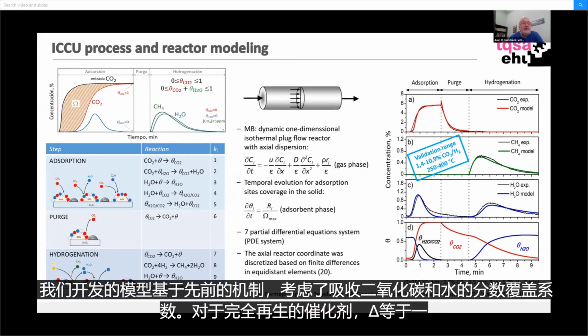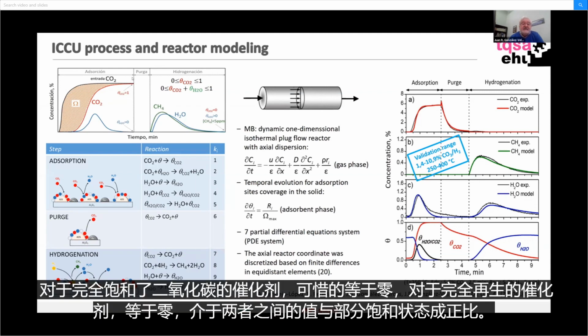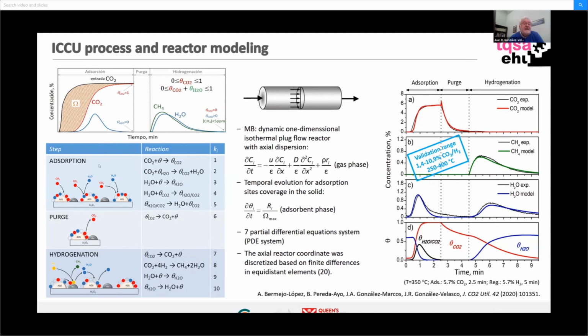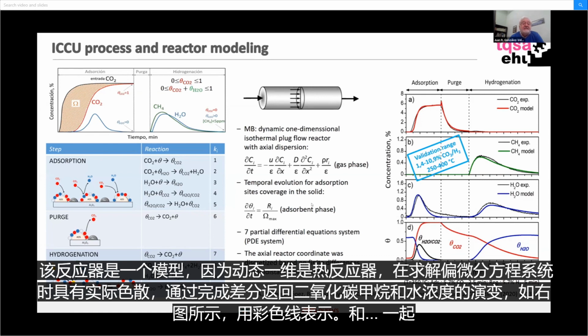The model we developed is based on the previous mechanisms and considers fractional coverage factors for absorption of CO2 and water. Theta equals 1 for catalyst fully saturated with CO2 and 0 for the fully regenerated, and values in between proportional to the partial saturation state. The reactor was modeled as a dynamic one-dimensional isothermal heterogeneous plug flow reactor with axial dispersion.